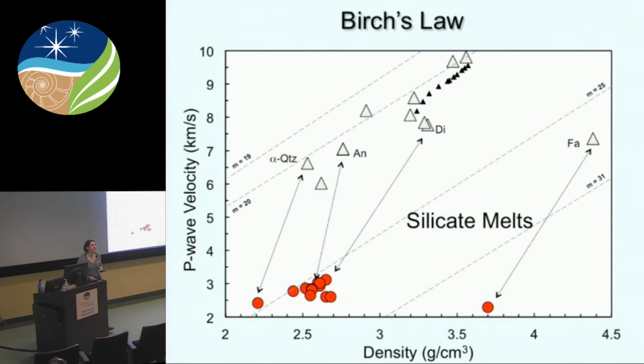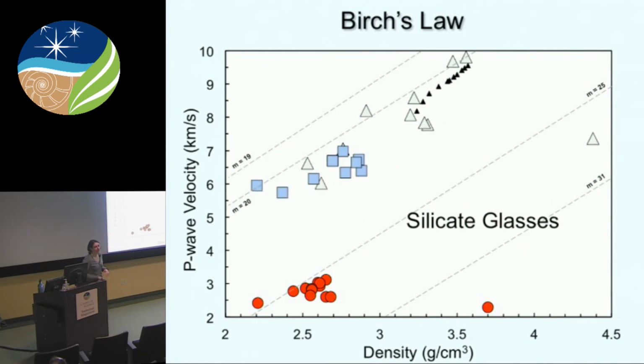Measuring the velocity of liquids at high pressure is challenging. So most of our velocity measurements for liquids are at 1 atmosphere. But we can start to look at glasses to see how they behave to get some insight into the high pressure behavior of melts. So here are data for silicate glasses. You can see again, they're constricted to a very narrow velocity range. Similar to silicate melts, it's a higher velocity, but a very narrow range, regardless of density.